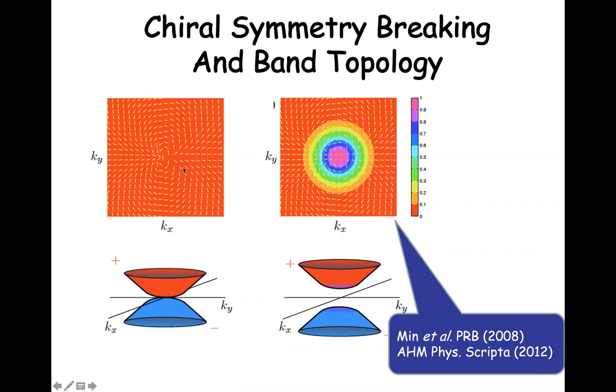So this is a plot on the left-hand side of wave functions as a function of momentum. The low energy states in a graphene bilayer are a linear combination of a component in one layer and a component in another layer, as I guess Eli first taught us many years ago. What this plot shows is that the wave functions, in this Bloch sphere representation, are a linear combination of a part in one layer and a part in the other layer, and that the phase relationship between the components in the two layers winds by 4 pi when you go around a circle in momentum space.